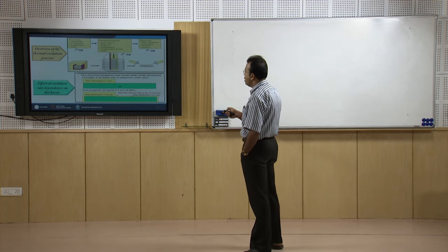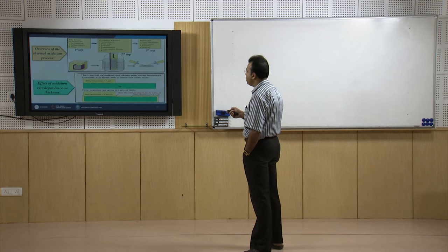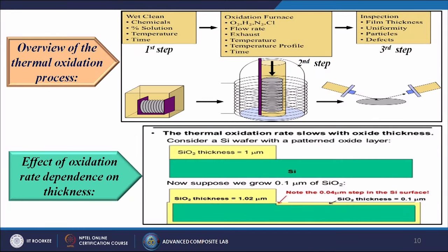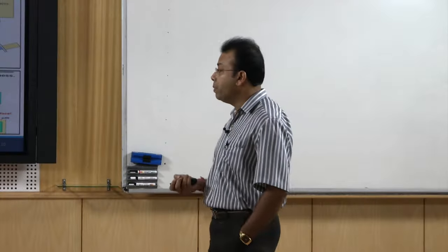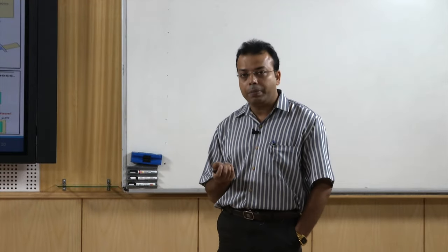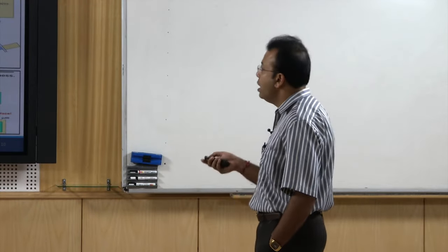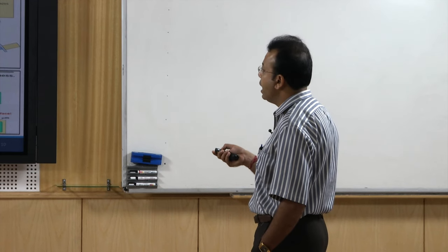First step, generally we do a wet clean by chemical process, by solutions, by temperature or by time. So we have to clean the surface itself. Then we have to put the material into the oxidation furnace in an atmosphere of oxygen, hydrogen, maybe nitrogen or maybe chlorine. Flow rate we have to maintain, exhaust we have to keep, and then we have the option to increase or decrease the temperature, because depending upon the temperature various chemical reactions take place, and then we have to keep the time.